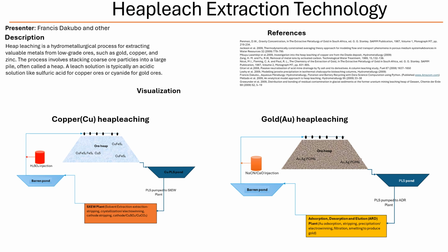Exactly. They even did microscopic analysis to confirm the presence of copper and cobalt within the ore particles. Wow, that's getting down to the nitty-gritty. And their leaching experiments really emphasize the importance of particle size. Big time. With a relatively high acid concentration, they saw a huge drop in copper recovery as particle size increased. But even with very fine ore, a low acid concentration just didn't cut it, so there's a balance to be struck. You need enough acid to drive the reaction, but grinding finer can be more effective than just using more acid. They also figured out a way to remove iron impurities from the pregnant leach solution by precipitating it out as lepidocrocite. And they did this without losing any copper.